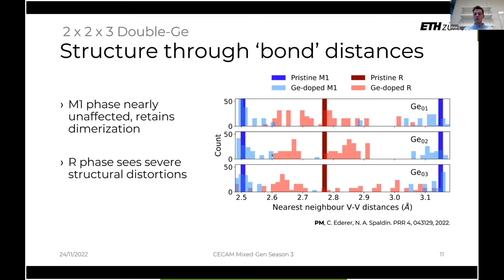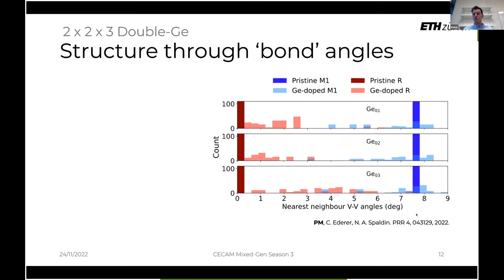Indeed, in the GE02 configuration, we see the formation of two peaks, and in GE03, we see a whole spectrum of different bond lengths, reaching from the shortest possible bond lengths that we saw in the M1 phase to the longest possible bond lengths in the M1 phase. And the story is the same if you look at the bond angles. These are the angles that these nearest neighbor vanadium-vanadium distances make. In some sense, this is a quantitative measure of the caterpillar-like shape I was showing before. Again, although the picture is less clear in these angles than in the distances, we see that the monoclinic phase retains some sort of finite angle, which seems to have some distribution around a finite value in all of these configurations.